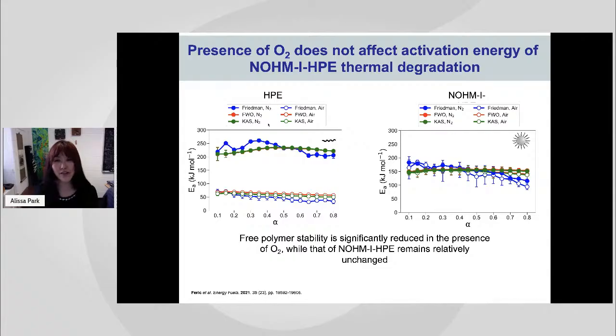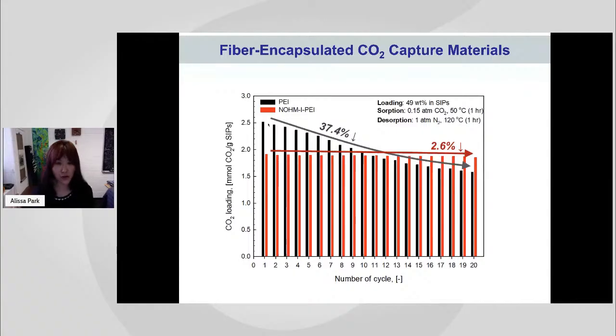So we start to see that NOHMs have really good potential as direct air capture materials. And it shows in the long-term stability, which we did about 20 cycles. Now, looking at the other challenges we talked about, like a low pressure drop.